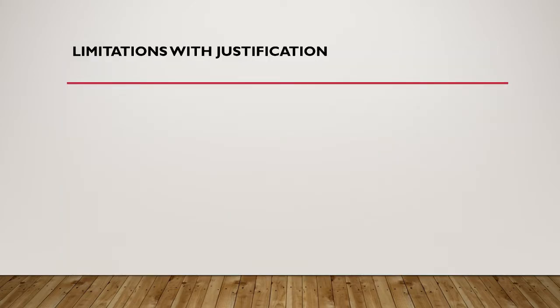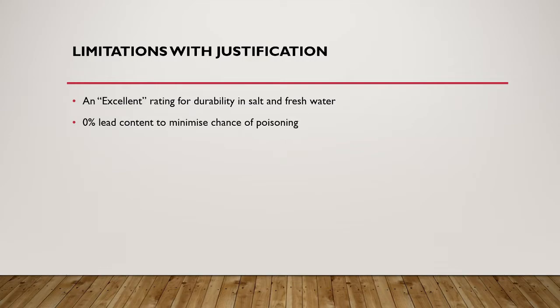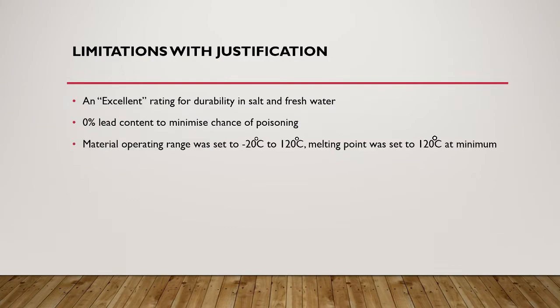We choose to impose a few limitations to eliminate unsuitable materials, including any material that's very susceptible to corrosion in water, any material with very high lead content, any material that cannot operate between negative 20 degrees Celsius to 120 degrees Celsius, and the melting point was set to 120 degrees Celsius to avoid melting during operation. We removed glasses and ceramics to avoid brittle fracture.